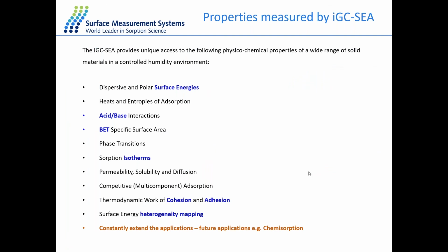So there's a few different properties that we can measure using iGC-SEA. The most common is the surface energy. And because we're using acidic and basic probe molecules, you can also have an understanding of Ka and Kb, the acid-base interaction. We can also determine the BET specific surface area, phase transitions, and also sorption isotherms. We can also measure things like work of cohesion and adhesion. Because we can inject multiple injections and concentrations across the surface of the sample, we're also able to obtain heterogeneity mapping across the surface.